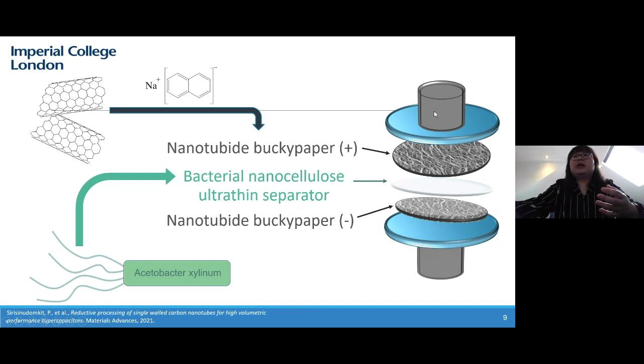So in my full cell device, the nanotube Bucky paper not only acts as the electrode, but also the current collector. In this case, we can remove other current collectors. That means we can reduce the mass of the overall system, as the nanotube Bucky paper is conductive enough and can behave as a current collector itself.